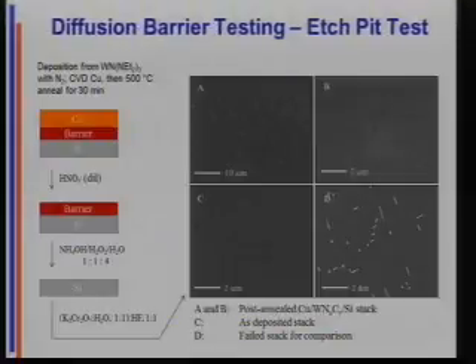And so how do you do diffusion barrier tests? Well, here's one of the ways. So we take the silicon substrate, we grow the material on there, we can put copper on the top either by CVD or by sputtering. You heat that to 500 C for 30 minutes, and then you start peeling off the layers. So we remove the copper with nitric acid, so it's just barrier and silicon. Then we dissolve off the barrier with basic peroxide, and then you treat it with dichromate and HF. And if copper has diffused through the barrier, it's made copper silicide. And the copper silicide is etched away by this reagent.